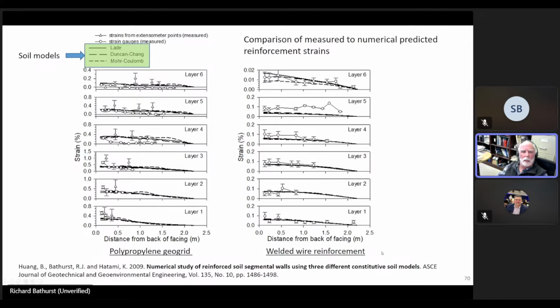welded wire reinforcement. And what we were interested in, in this particular study, was looking at the influence of different soil models on the predictions of strain in the reinforcement and their comparison with measured results. So what you can see is that in general, again, we judged that the predictions were in reasonable sympathy with the measured results. We also deduced from these particular tests that we didn't really have to worry too much about the actual constitutive model for the soil we used, because we were dealing at the end of construction of the structure, where the strains in the reinforcement are quite low.